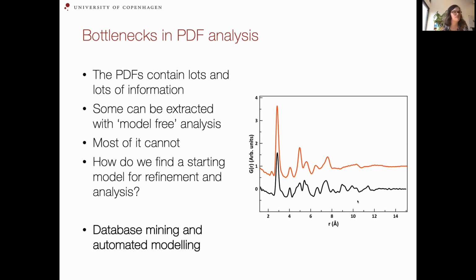Because I said before that this is an intuitive method of analyzing structure-wise, but you can usually say what the first couple of peaks are, but when we get further into r space, well, then it gets much harder to assign those. So we always end up sitting and testing a million different structures, or tens or hundreds of different structures, and seeing what fits best. So what we are working a lot on is to automate these methods.